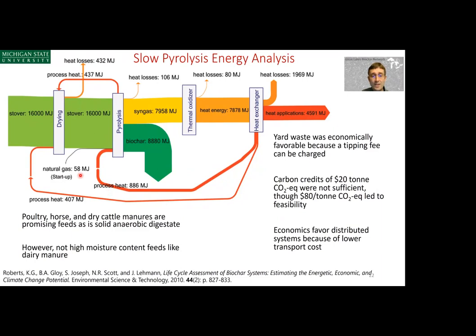You can see these recycled heat lines here. Note, the amount of process heat needed for pyrolysis is not that great. You have to add some energy to raise the temperature to the ignition temperature of pyrolysis, but once it gets started, it's fairly self-sustaining, so it's not very energy intensive to run.